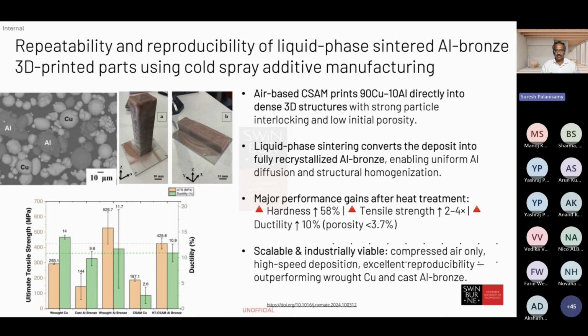I think I went too quickly there. So these are some of the different properties that can be achieved. What I'm trying to highlight here is, as you can see, if you can heat treat the cold spray additive manufactured part, especially with aluminum bronze, it can achieve close enough to the wrought properties, which is good enough here. And it's also far better than the cast aluminum bronze properties.